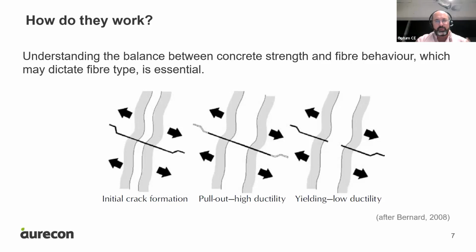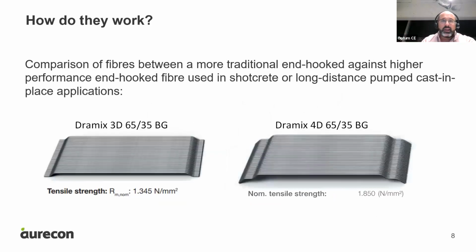But this is a concept that we need to bear in mind: fiber type and fiber strength need to be compatible with your concrete strength if you want to maintain the same level of ductility, or even better, when we're moving towards a higher strength concrete. Here's an example. Until maybe some 8-10 years ago in Sydney practice, the very common fiber that we